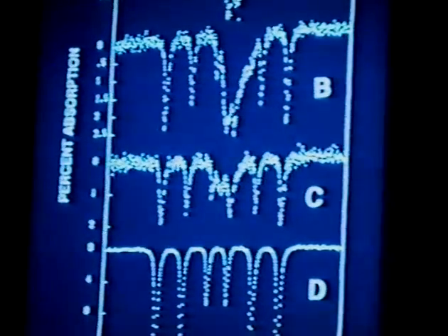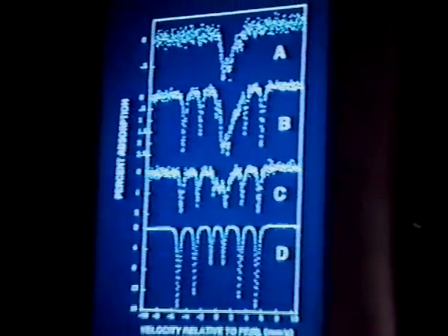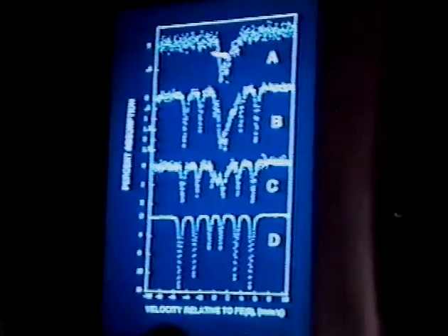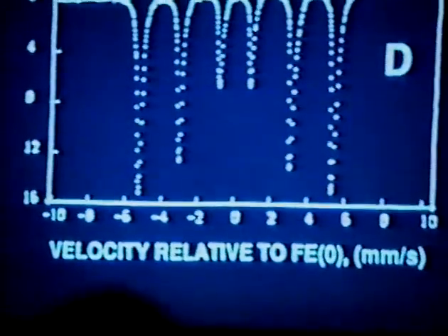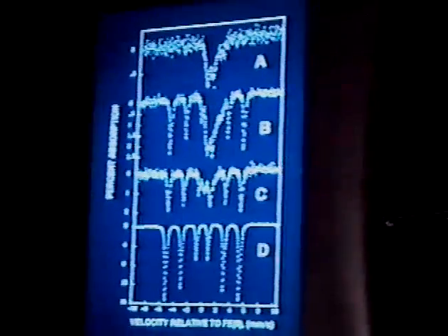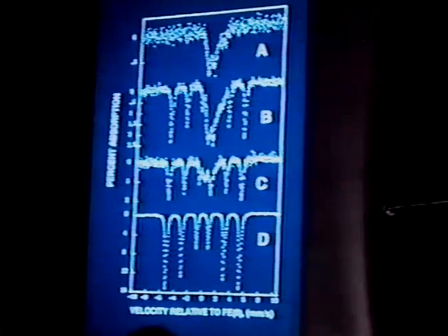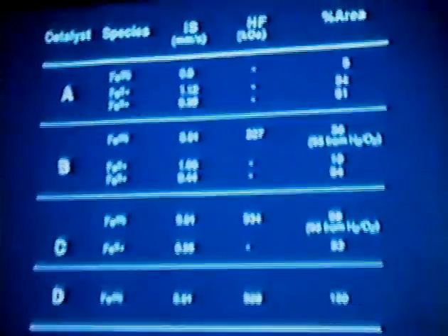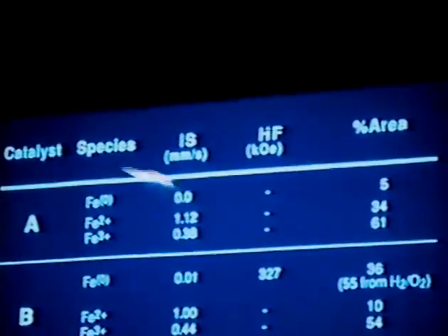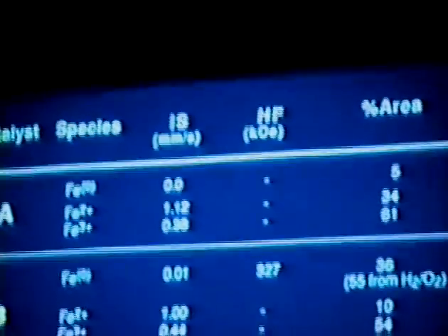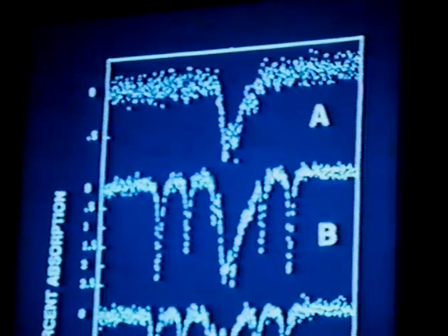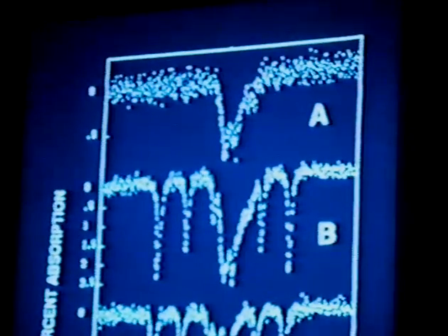Now, these are the Mössbauer spectra for these three catalysts that I showed in the previous slide. The first one is for the catalyst prepared on support dehydroxylated at 200 degrees centigrade. This one, 650. And the third is for the one that was dehydroxylated at 800 degrees centigrade. And this is a pure iron foil that we use to standardize our spectrometer. And these are the curve fit parameters for these catalysts. And as you can see, the iron 0, which is only about 5% of the area of the first spectrum, indicates that the iron present here is superparamagnetic.